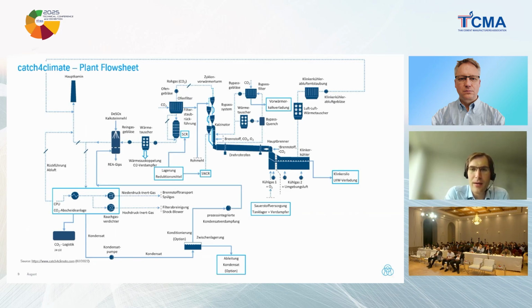And that really renders this project with a high degree of complexity, no matter whether it has a capacity of 450 tons per day or 4,500 tons per day. There's also this newly developed bypass cycle. There's a multi-stage flue gas cleaning, including NOx reduction, including SOx, mercury, etc. And in this degree of complexity, this is really something new for the cement industry. Also, there is a much stricter standard on the flue gas composition after cleaning at the interface to the CO2 purification unit.